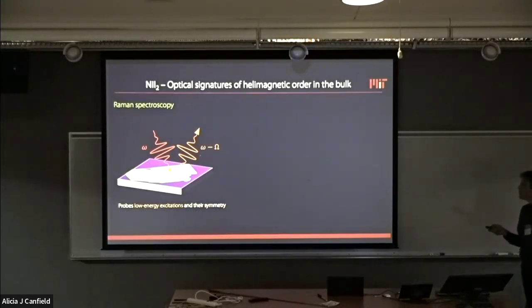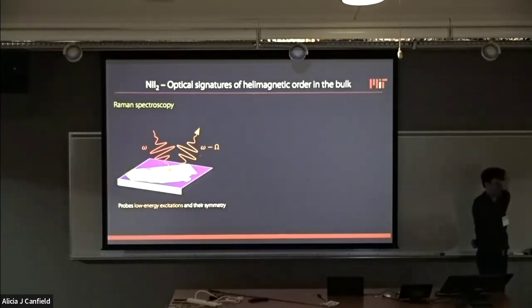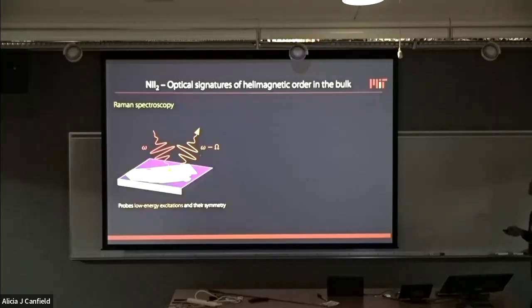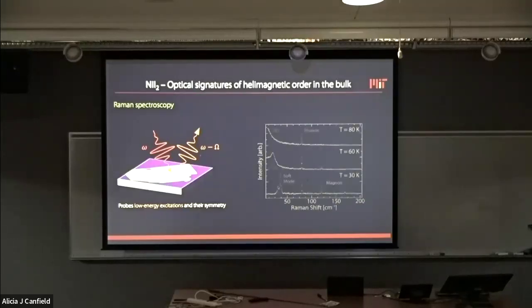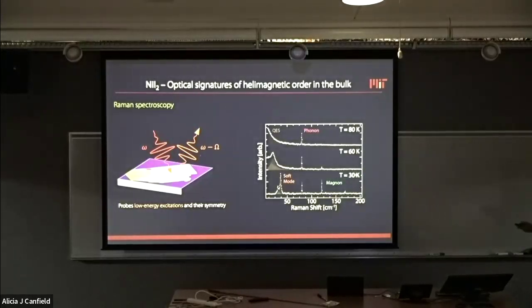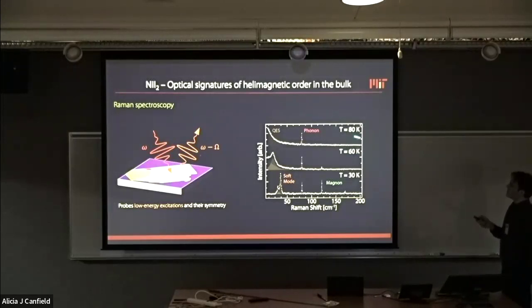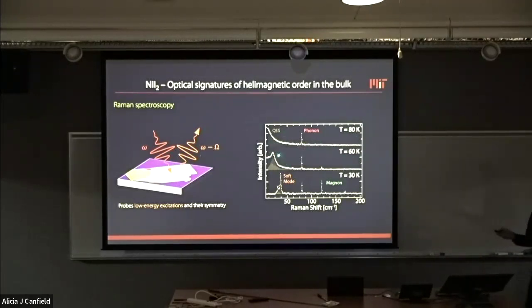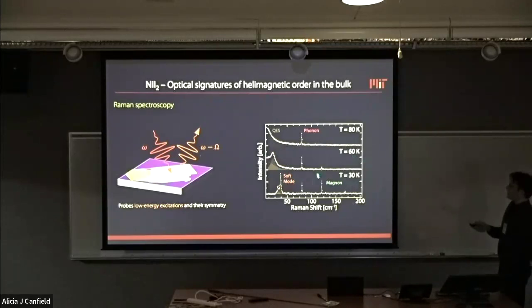And then with Raman, we did a Raman experiment to look for the signatures in the low energy excitations, because one thing that is missing so far, and this goes back to Igor's question about whether we can tell it's a cycloid or a helix, is that we haven't yet shown that the ground state is chiral. So that's where Raman came to the rescue, because we did these experiments as a function of temperature. At high temperature, there's not a lot that's very interesting. There's a phonon, and then some sort of quasi-elastic scattering, which is probably from some very low frequency spin fluctuations. And then at 60 Kelvin, at the helimagnetic transition temperature, there is an electromagnon that branches off from this quasi-elastic peak. Then the electromagnon hardens and becomes sharper. So it goes from being overdamped to being essentially a quasi-particle-like excitation at low temperature.